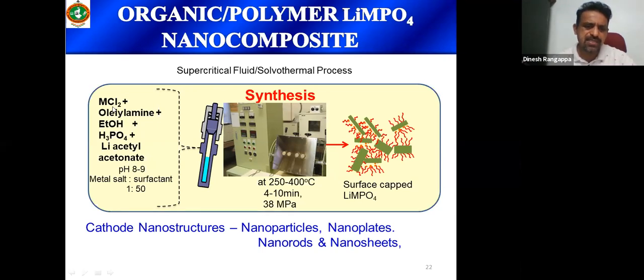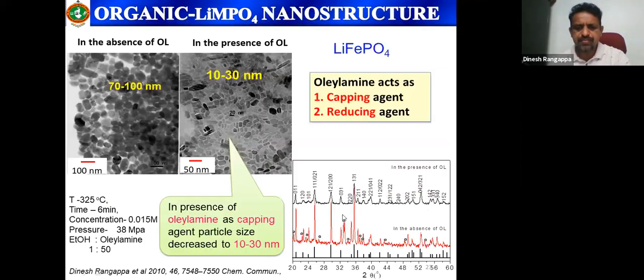You can see metal salts, iron chloride and lithium acetylacetonate, along with phosphoric acid and ethanol were taken, and the pH was adjusted to basic. Then oleylamine, a surfactant to control the size and morphology of the nanoparticles, was used at a 1:50 metal-to-oleylamine ratio. Then it was heated from 250 to 400 degrees centigrade for 4 to 10 minutes under 38 megapascal pressure. We obtained surface-modified lithium metal phosphates, and we could control morphology such as nanoparticles, nanoplates, nanorods, and nanosheets. Here you can see lithium iron phosphate synthesized with and without oleylamine. Without oleylamine, particle sizes were 70 to 100 nanometers, but with oleylamine, particle size was controlled to around 10 to 30 nanometers. Oleylamine also acts as a capping agent and reducing agent, and pure lithium iron phosphate was obtained.